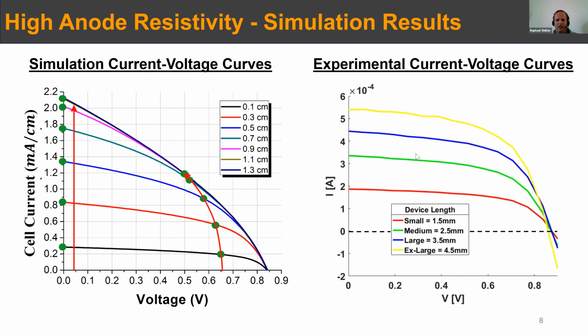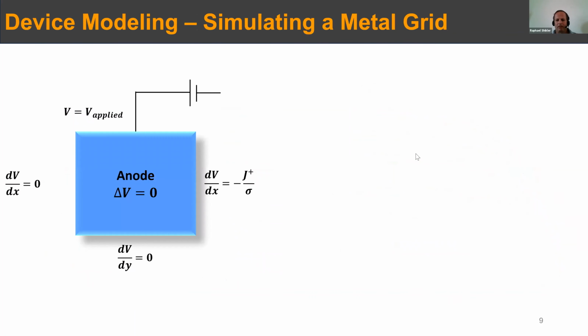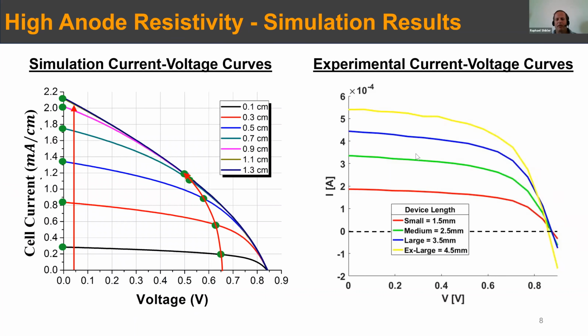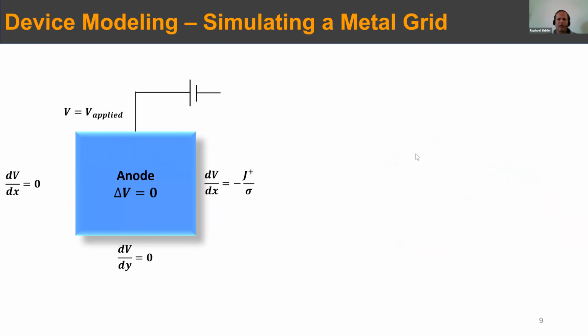And just to prove that we don't just do simulation, but also measure things, when you do this calculation and really fabricate cells, you can see that when you have a relatively small cell, you have a current, you increase the cell size, then the current really jumps. And when you increase it further and further, the jump in the currents becomes smaller and smaller. Now, this is not new, only the calculation idea was new.